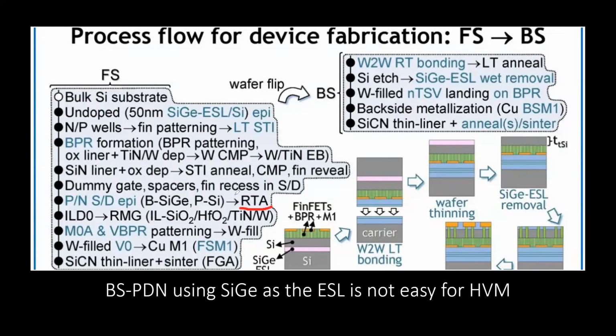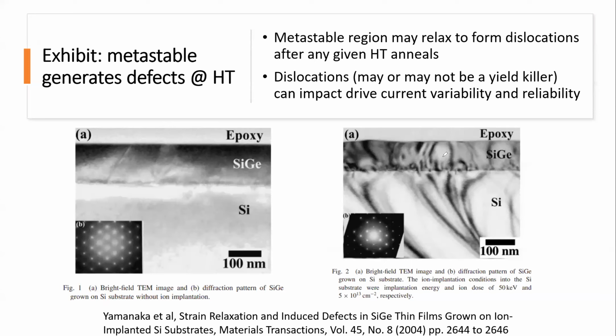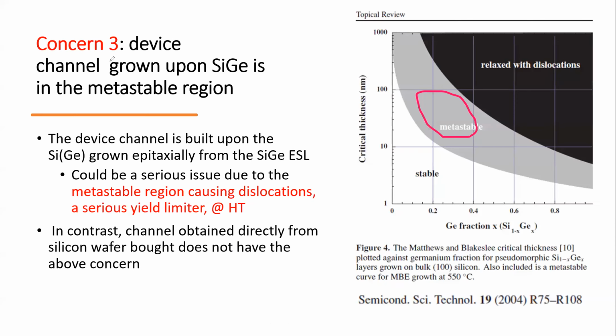I see this is RTA here. So this is the dopant activation temperature. This is pretty high, okay, and for a very long time. So all these are concerns, and it will relax if you give it a chance. So you need to be very careful. You cannot trust yourself that it is initially very nice and will stay that way. That's not true, because it may not stay that way if your process is not tuned and readjusted to reflect that you need to protect this layer. Okay, that's what I meant by concern 3.